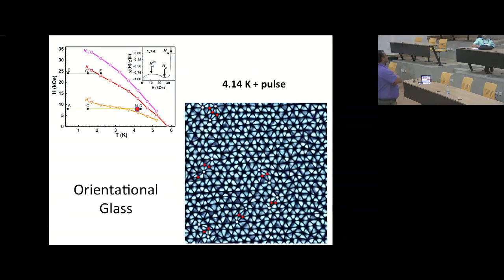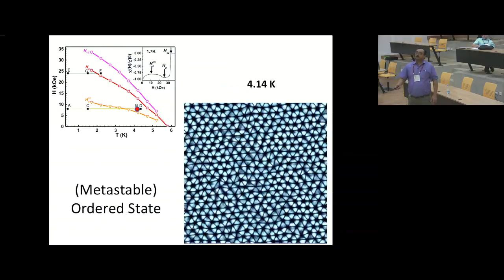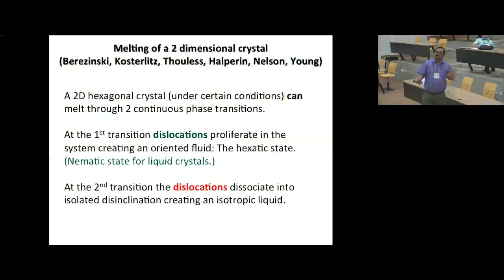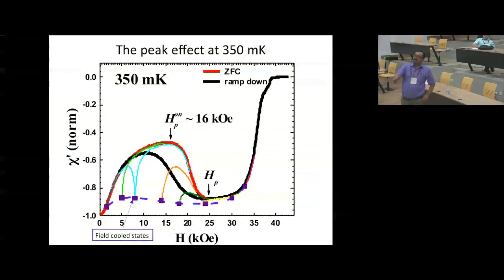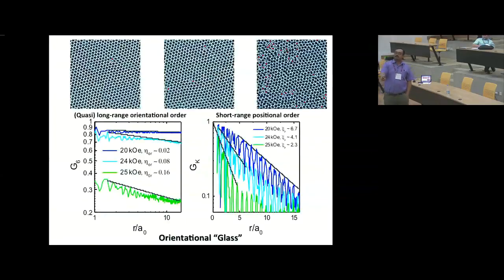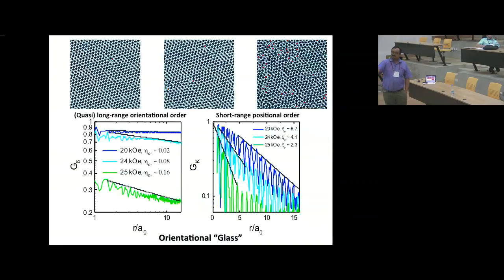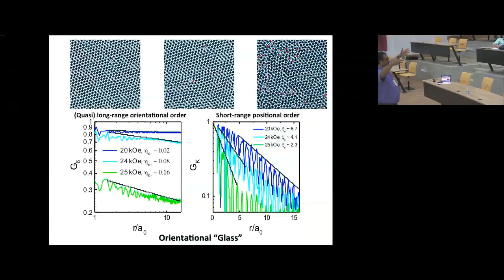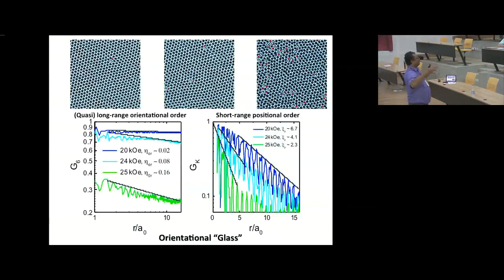Pratap, is it true that there's no phase here where you see algebraic decay in both the positional and the orientational correlation functions? Okay, that's a very interesting question. In some of the disordered samples we had observed, and this is actually one such disordered sample, that this is algebraic decay. And here there is an exponential decay, but if you believe the large distance decay, that becomes more algebraic. I see. So it is not ruled out, but I cannot say with 100% confidence because this becomes close to the edge of the image, and the confidence level will drop.